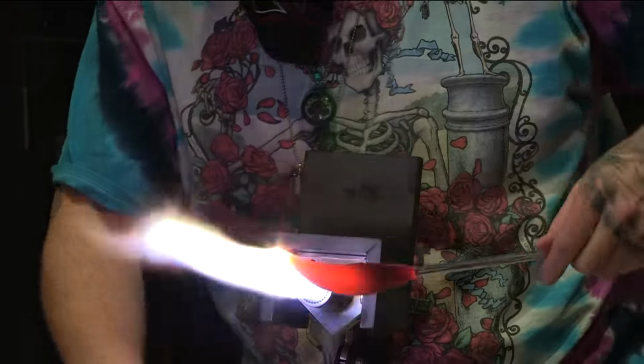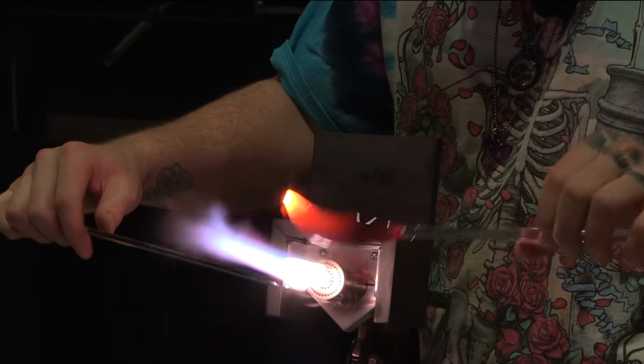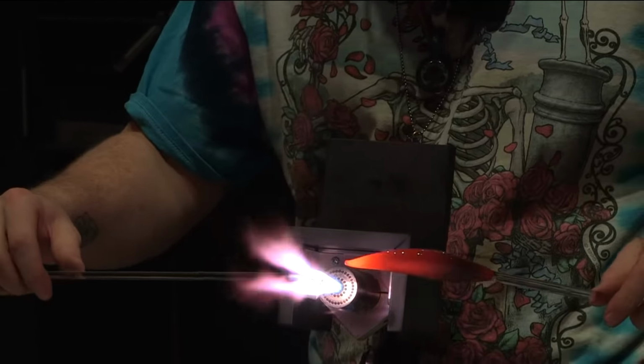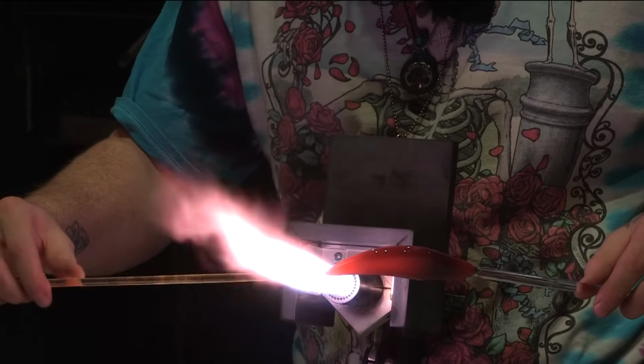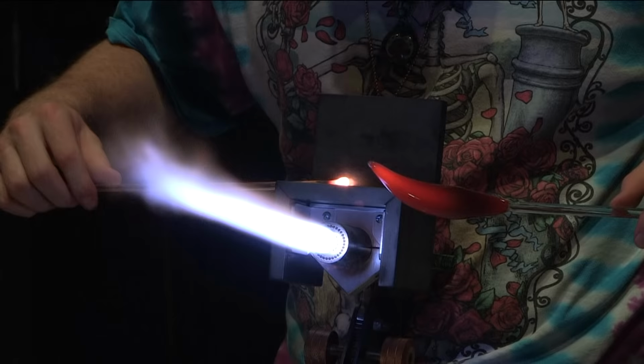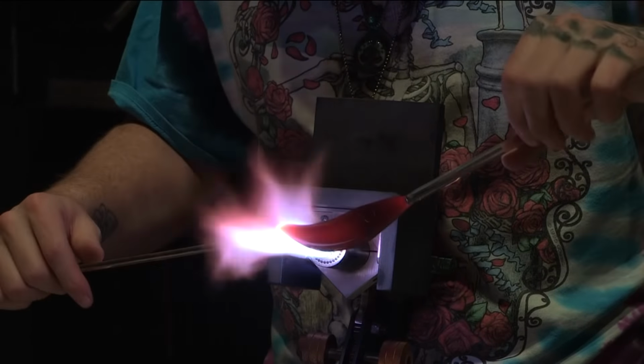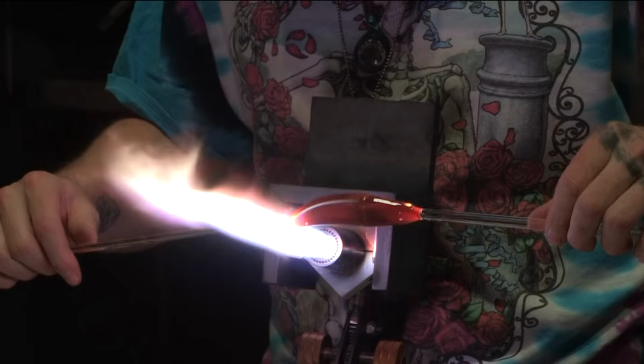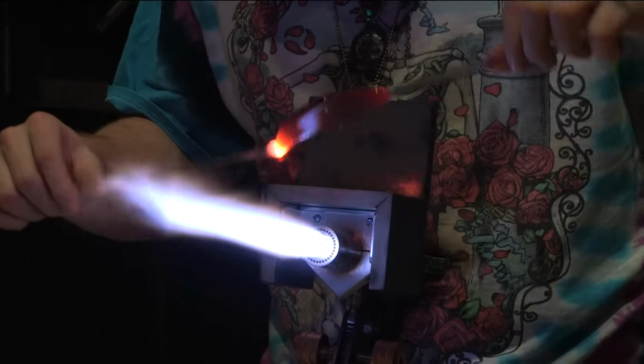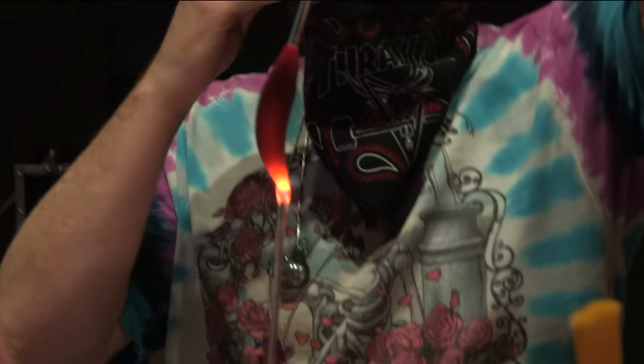They can balance it a bit with the flame. I mentioned earlier, sometimes you'll see these guys using the blue flame to really melt the glass and shape it. Other times you're going to see them adjust that flame to something that's yellowy, a little more billowy. They can use that yellowish, billowy flame to soak some gentle heat throughout the whole piece. As things warm to the same temperature, they balance out their stress. And also they're using the oven to reduce a lot of that stress as they go along as well.